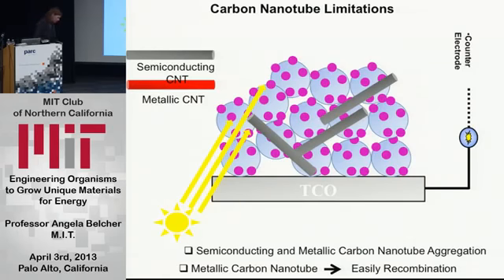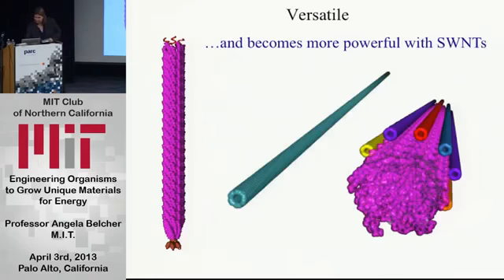The other thing with this is that carbon nanotubes are very hydrophobic, and in solution, they will form aggregates and they'll collapse together. And we said what we want to do is we want to pull them apart, and then maximize their interaction with the titanium nanoparticles. And so we said a virus could solve this.